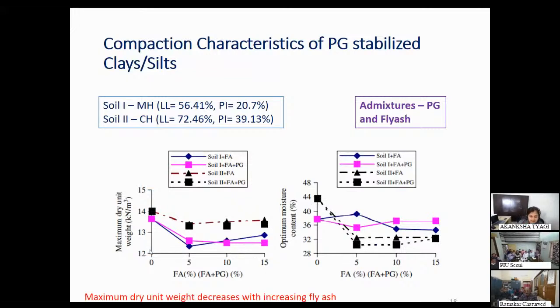Now, why did the maximum dry unit weight decrease when we add fly ash and the phosphogypsum, or only fly ash? Even if you are replacing fly ash by 50%, the results are quite close. So the thing is, fly ash has a lower specific gravity, and that is why the maximum dry unit weight decreases when we add fly ash to the clay type of soil or silty type of soil.